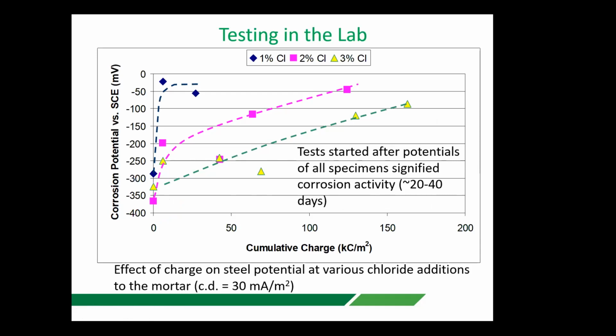And what we found was that depending on the amount of chloride that we've contaminated the sample with, if we only had 1% chloride, and in fact that's slightly misleading because in the lab it's very difficult to induce corrosion at 1% chloride, although in practice that happens very regularly. In the lab, using small samples, you tend to make them a lot better than what you would make them on site.